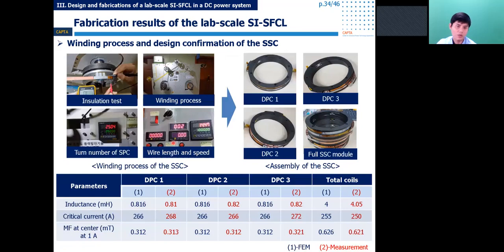Next is the secondary coil fabrication. It will be wound on the aluminum bobbin and co-wound with the Kapton film. After winding, the critical current and magnetic field were confirmed when cooling the coil in liquid nitrogen. All the measurement results are summarized in this table. You can see they were similar to the FEM simulation result.